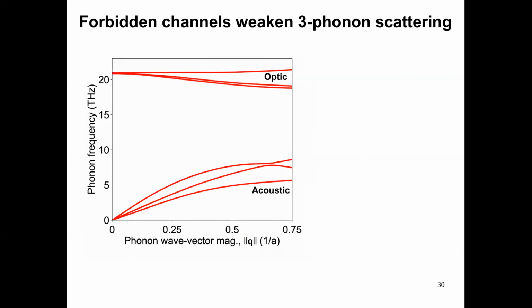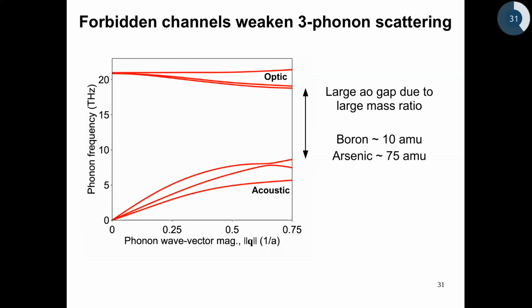Let's go back and think about it from the dispersion perspective. Here I am showing the phonon dispersions for boron arsenide. You have 3 acoustic and 3 optic branches. And because boron arsenide has a large mass ratio between boron and arsenic, you have a large gap in frequency separating the acoustic and the optic phonons.